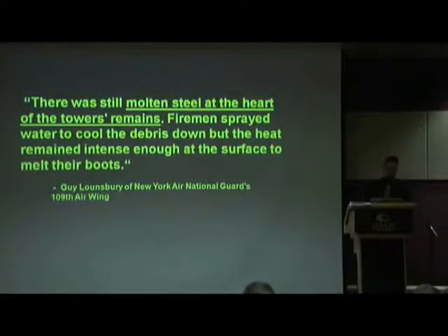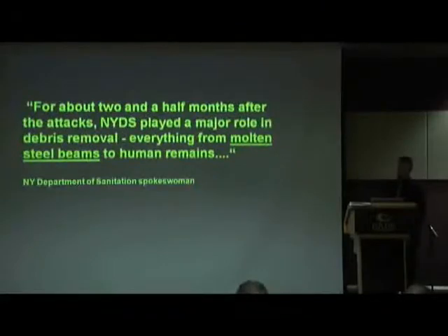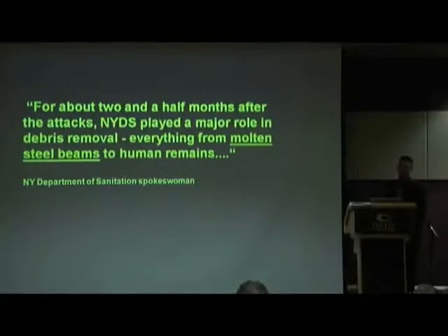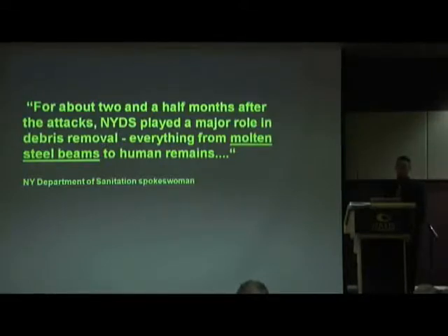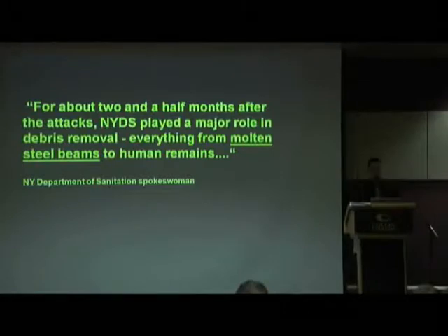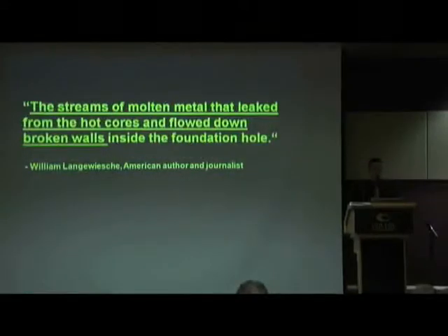Guy Lounsbury of New York Air National Guard's 109th Air Wing. Molten steel at the heart of the towers remain. Firemen sprayed water to cool the debris, but the heat remained intense, enough at the surface to melt their boots. New York Department of Sanitation spokeswoman. Molten steel beams. Everything from molten steel beams to human remains. For about 2.5 months after the attacks. American author and journalist William Langewiesche. The streams of molten metal that had leaked from the hot cores and flowed down broken walls inside the foundation hole.